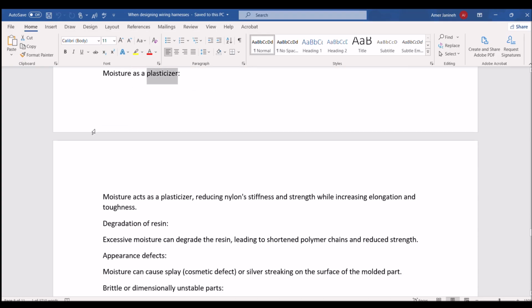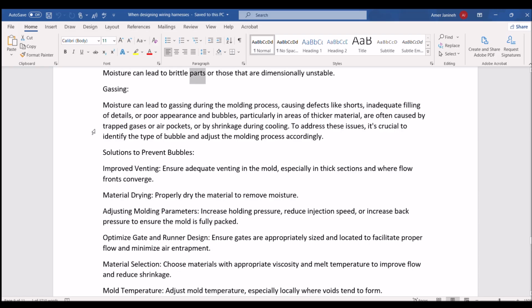Moisture as a plasticizer. Moisture acts as a plasticizer, reducing nylon's stiffness and strength while increasing elongation and toughness. Degradation of resin. Excessive moisture can degrade the resin, leading to shortened polymer chains and reduced strength. Appearance defects. Moisture can cause splay, a cosmetic defect, or silver streaking on the surface of the molded part. Brittle or dimensionally unstable parts. Moisture can lead to brittle parts or those that are dimensionally unstable.